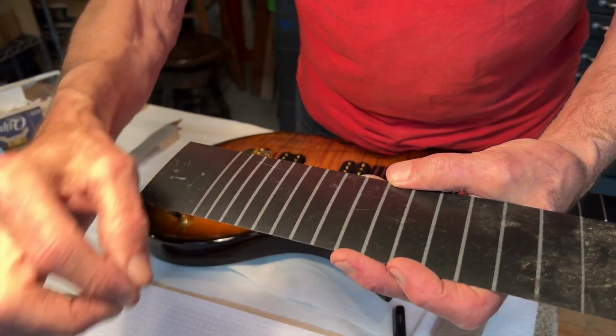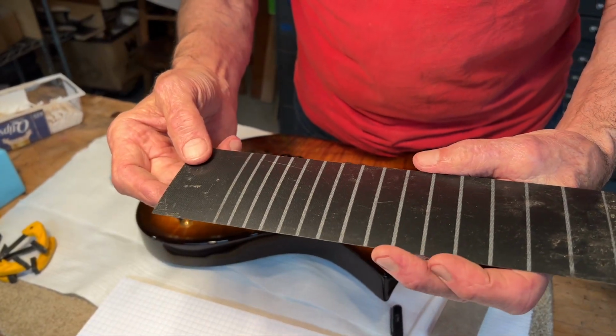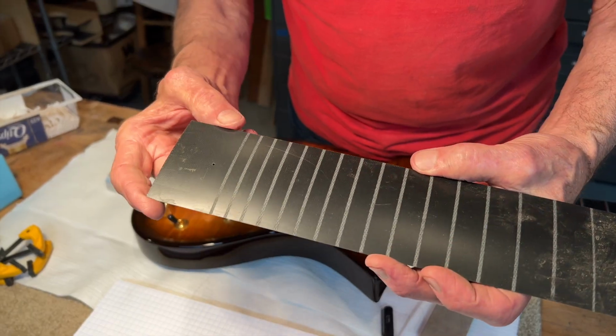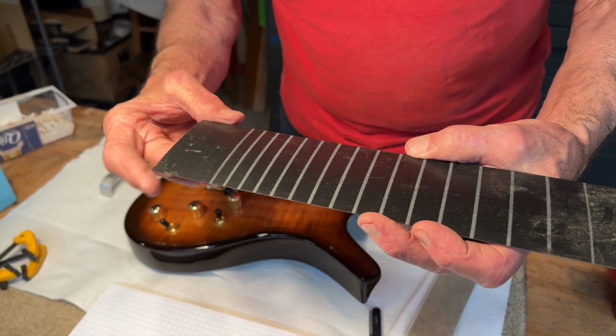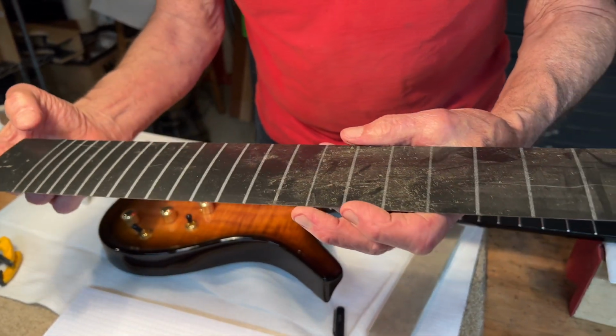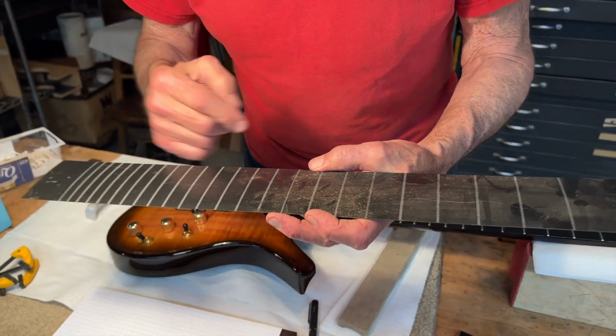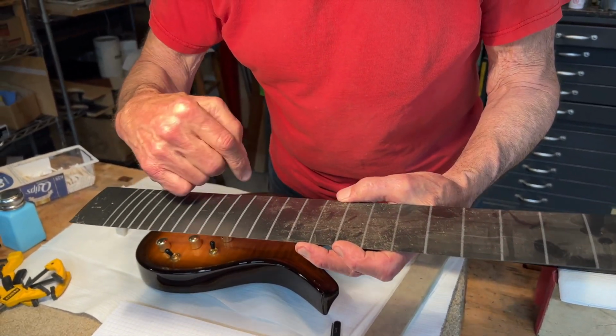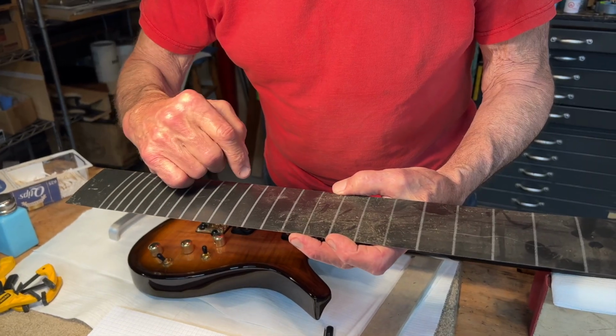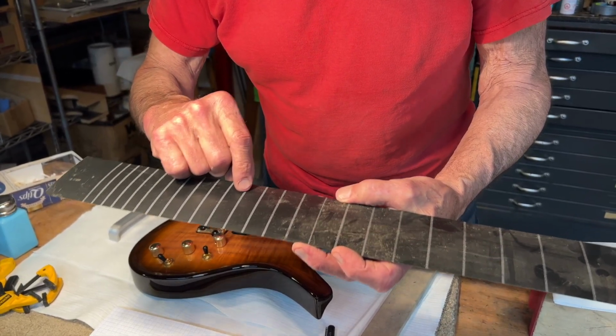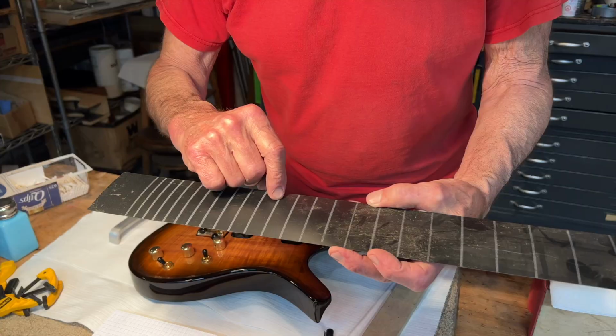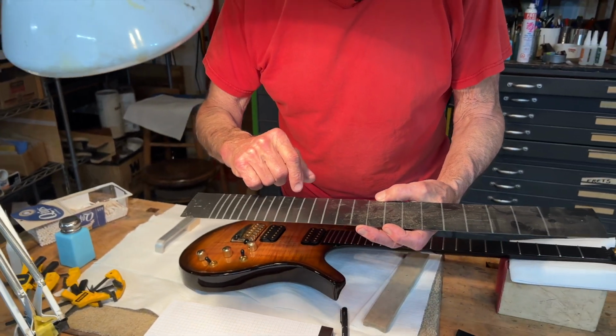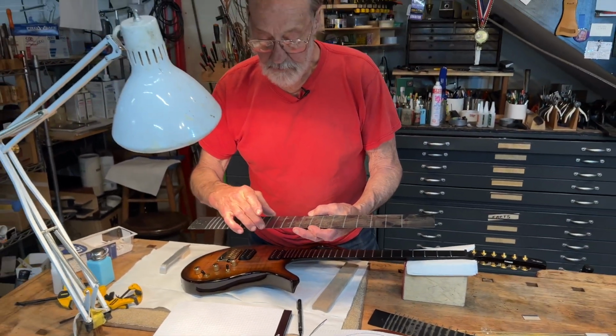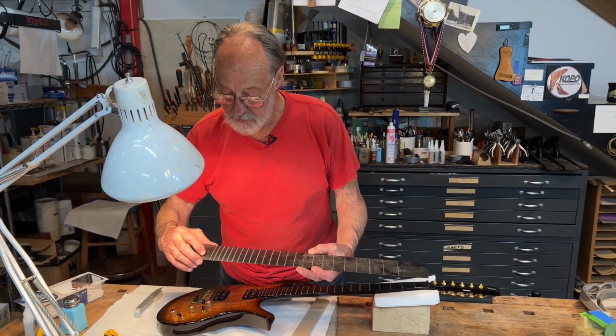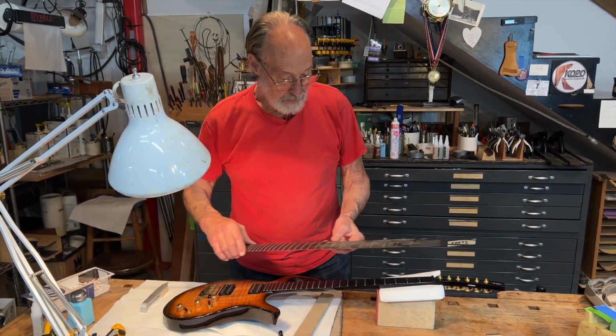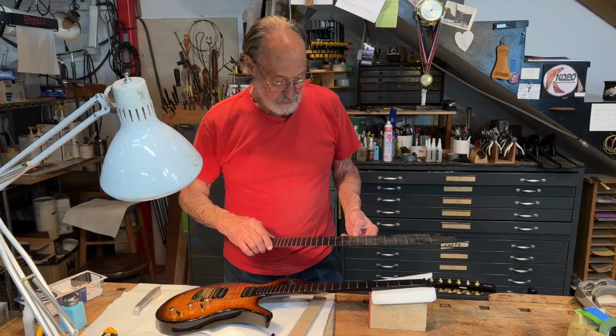First we did it with sandblasting, and that was kind of a mess and difficult. And then we finally ended up doing it with a laser, which was pretty fancy 30 years ago. But anyway, that's how we did it. So the laser would go in there at low power and blow away the hardened adhesive and expose the glass fibers. And then we could get a good bond to the glass fibers and not play around with trying to bond to the resin surface. Okay, so I think I've told you.